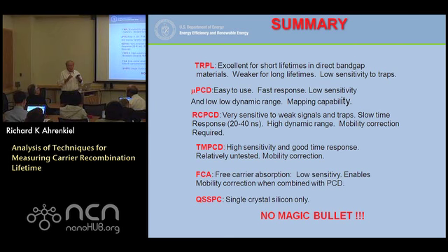Now, most of the gallium arsenide I look at anymore has gallium indium phosphide, so it's very low surface recombination velocity. If I looked at a bare film like we did 20 years ago before gallium indium phosphide came along, yeah, in fact, that was the subject of some contention way back when I was first at NREL, where certain researchers said they had good gallium arsenide solar cells, and we measured it, and we didn't know any better. No, they're not. It was really the surface effect.